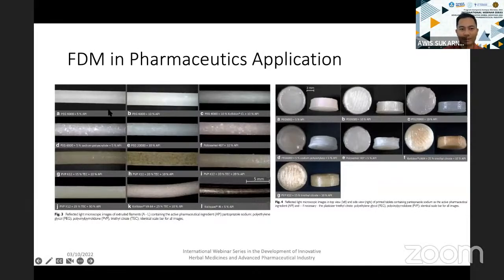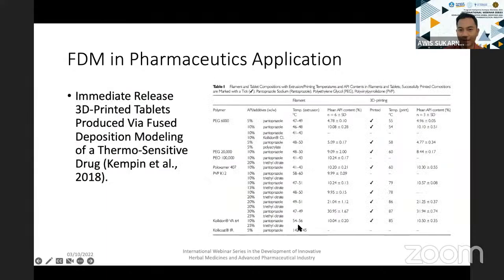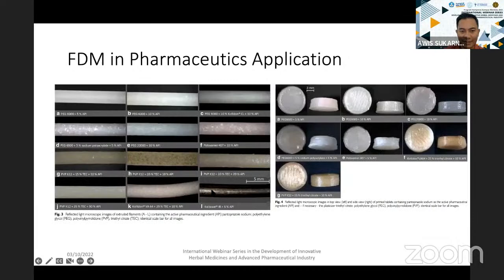You can see the filament here is quite nice, and from here you can see this one is basically the API that is suspended on top of the filament. And from here, the Kollicoat IR, because like I said, this one is the only sample here that has quite a high temperature for the melting point. So you can see the color is quite dark, which means the sample or the active ingredient is already degraded at this point. So that's why it showed a charred color, a black color here. Then from here they chose the best one, and then they printed the tablets, and you can see here they showed quite a nice shape, except for this one, the poloxamer. The shape is a bit wonky, but the best one is actually the PVP K12 here. It shows a very sharp image, followed by the PEG 6000.